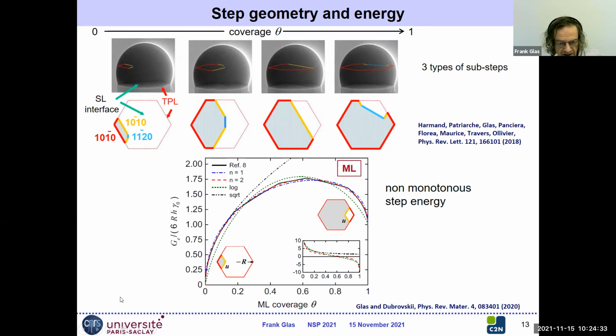And the result of all this is that here the energy of the edge of the monolayer as a function of monolayer coverage, so size of the island, does not increase as the square root, as would be the case in a monolayer which would extend infinitely. Actually, it increases non-monotonically. At the beginning, it looks very much like the square root, but then we reach a maximum, and then the energy starts decreasing until the monolayer completes. So that's a consequence of these various segments and their various energies. So very important, we have a non-monotonous step energy as a function of the monolayer size.